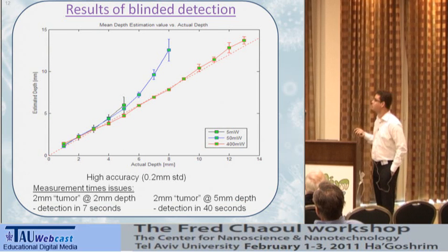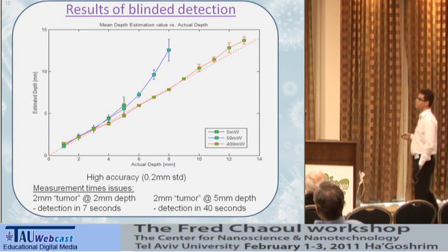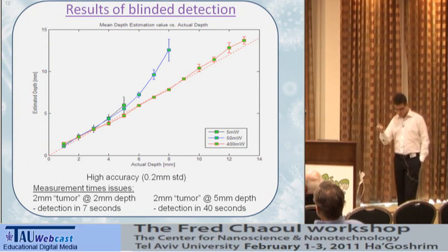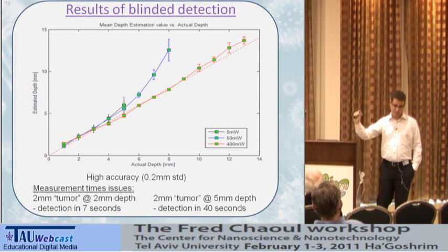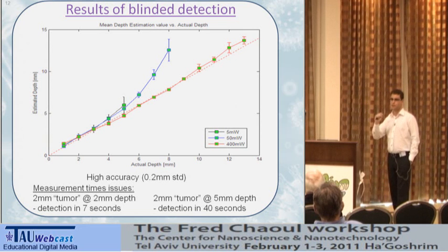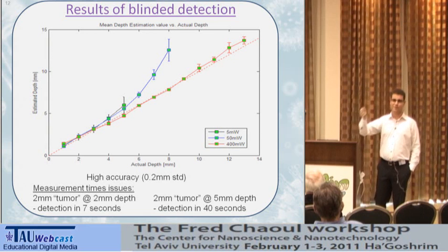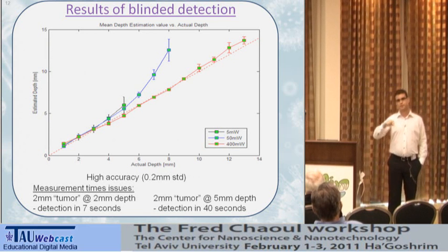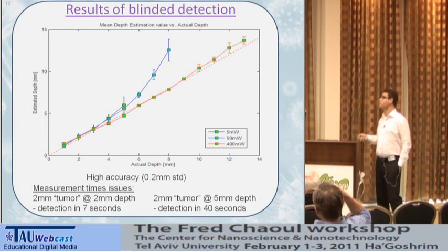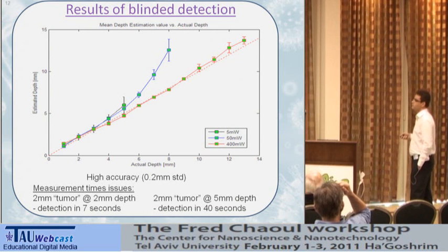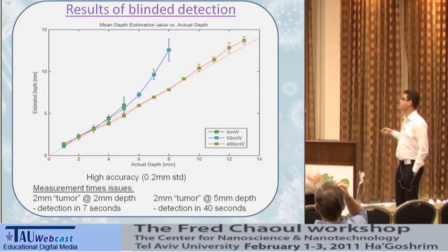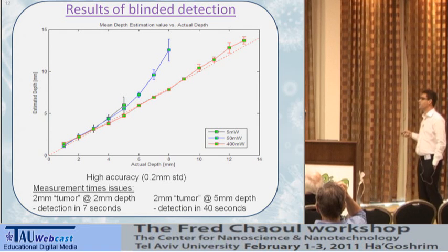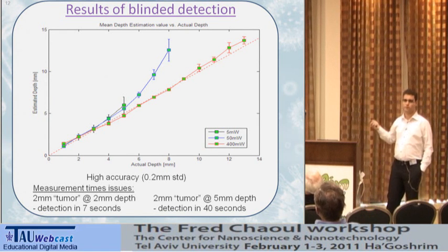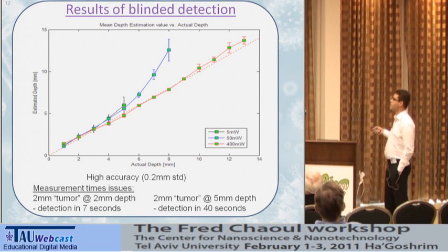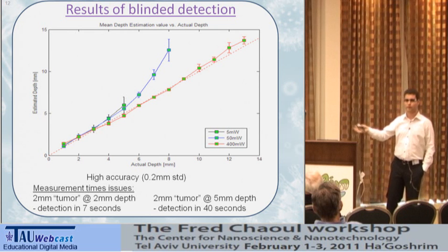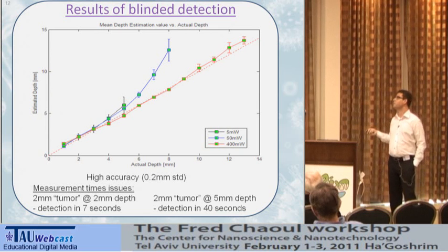However, we had some problem with these measurements. It was timing issues. If I want to detect the tumor and I look at the temporal development of this hotspot pattern, I need to wait long enough to see that this pattern behaves like my simulations. And the deeper the tumor is, the longer it takes for this pattern to develop. So for a 2 millimeter depth tumor, in only 7 seconds I can tell you whether it's a tumor or noise. For a 5 millimeter deep tumor, it takes 40 seconds and it rises exponentially. So this is a problem if I want to detect in a real situation and I need to scan throughout the entire body or at least throughout the entire organ. This might pose a problem.